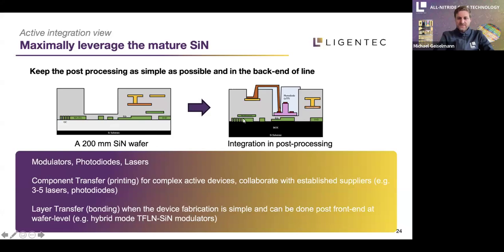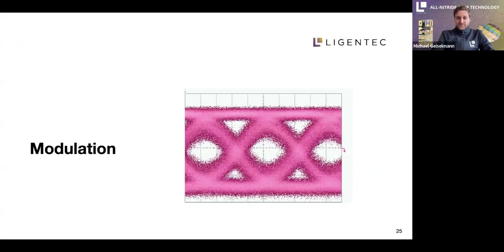And so one integration is what is shown here, is the integration of photodetectors that we're doing with component transfer printing for complex active devices, where we collaborate with established suppliers for III-V lasers or photodetectors. And in other approaches, we do layer transfers like bonding when the device fabrication is simple and can be done post front end and at wafer level. For example, our hybrid mode thin film lithium niobate silicon nitride modulators that I will introduce in a few minutes. So we have modulation, detection, and lasers that we want to integrate in this very low loss silicon nitride platform.